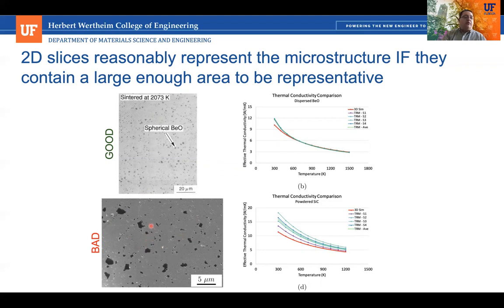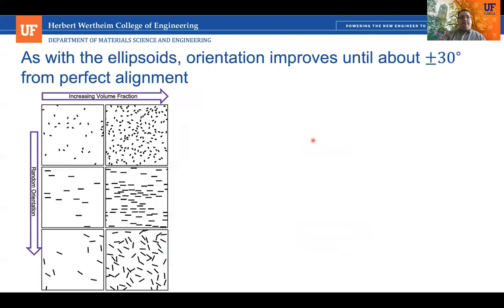So it's not a representative microstructure of the material, which leads to this large scatter in the different slices of our 3D microstructure. And it also resulted in our model being less accurate. So as long as we have a good representative microstructure, then our model works well to estimate the thermal conductivity. And we can now use this idea of continuousness to try to design and help optimize microstructures that result in the best benefit for a certain amount of additive.